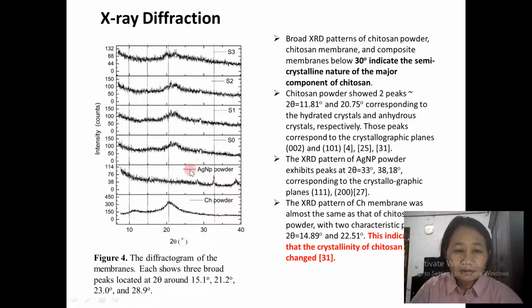Chitosan powder shows two peaks. The first is around 11.81, and the second one is around 20.75. These peaks correspond to the hydrated crystals and the anhydrous crystal. Those peaks correspond to the crystallographic planes 002 and 101.